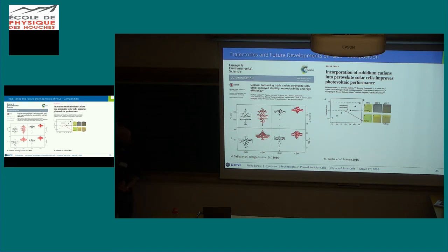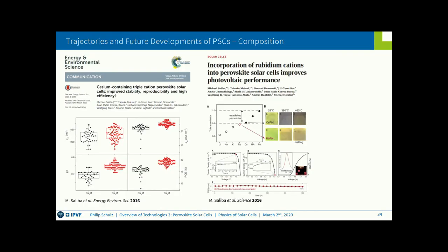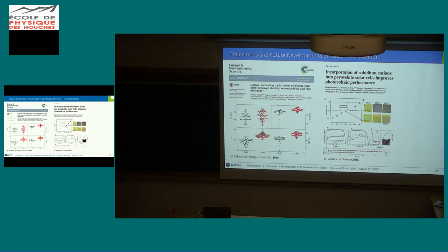So for us now, looking at the influences of all these different alkaline species, or alkali species, is a rediscovery of what people have already seen and learned for CIGS. So we're very happy to merge these communities to some degree. But in any case, what Michael was seeing, that when he added rubidium, not knowing where it really goes, he could increase the performance, but also get to really long-term stability, with the caveat here that the stability assessment over hundreds of hours was done in nitrogen atmosphere.